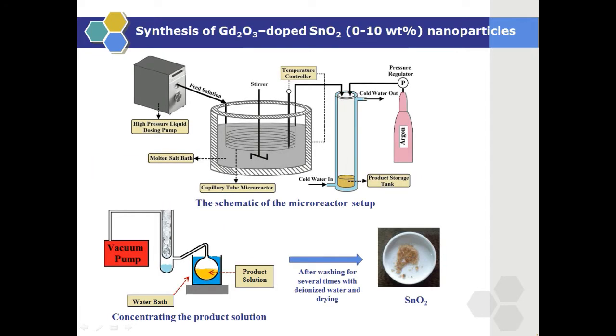Here you can see the microreactor setup that we use for synthesis of nanoparticles. The feed solution contains urea, tin chloride, and deionized water in ethylene glycol medium. The solution has only 5 seconds residence time in the capillary tube immersed in the molten salt bath.